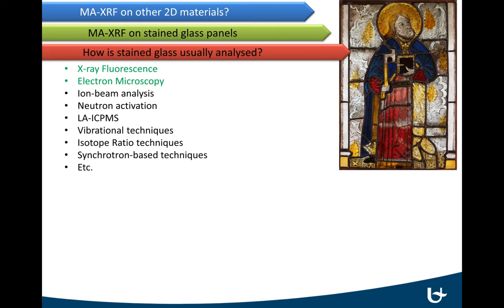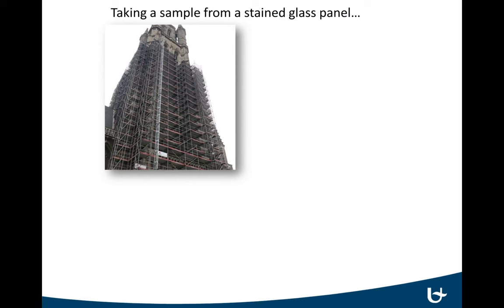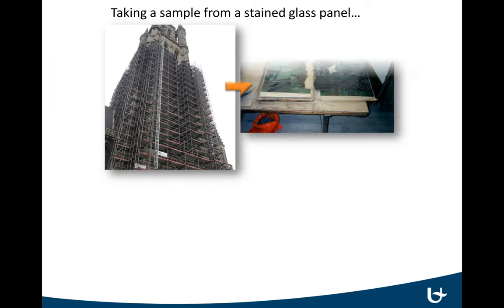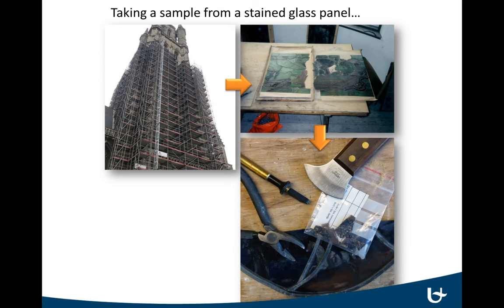In literature, a large number of techniques have been reported. The most popular methods are clearly XRF — which is good news for us — and SEM-EDX. What all of these techniques have in common is that they involve analysis on samples or small fragments. Most articles focus on the technique itself or on the results obtained, but none of them mention how difficult it can be to collect a consistent set of samples. Most stained glass windows are found in their architectural setting, so if you want to collect samples, you have to first overcome your fear of heights to remove the panels from the masonry. Then in the studio, you have to cut open the lead came network so you can reach the glass and fragments of interest, and then a number of tools such as glass cutters, diamond saws, tongs, and tweezers come into play — instruments we do not associate with the words non-destructive or non-invasive.